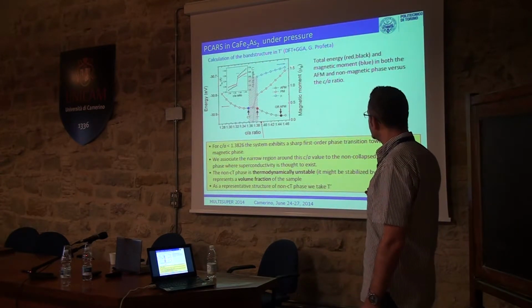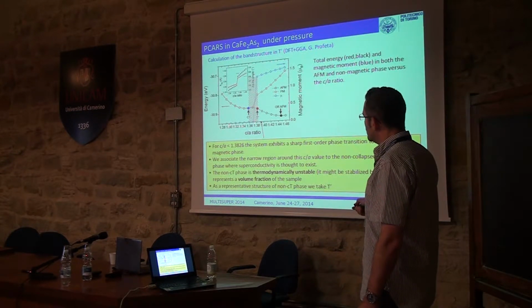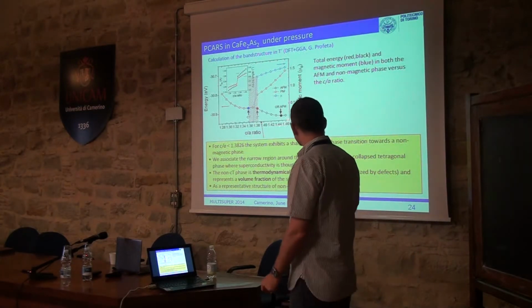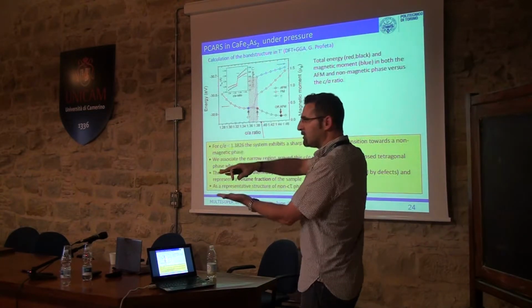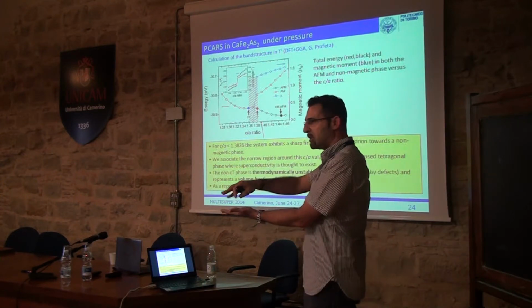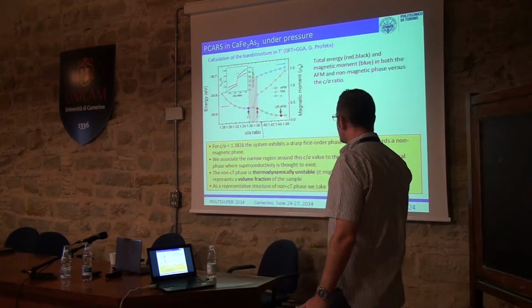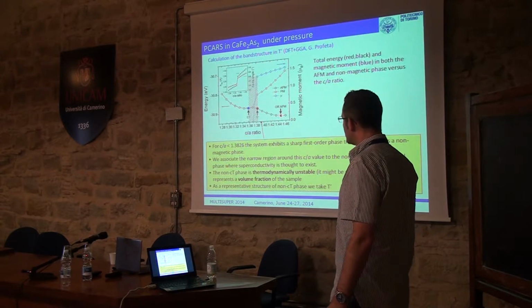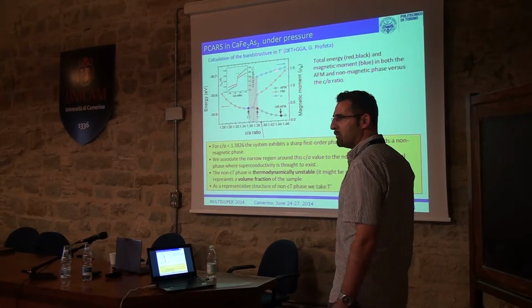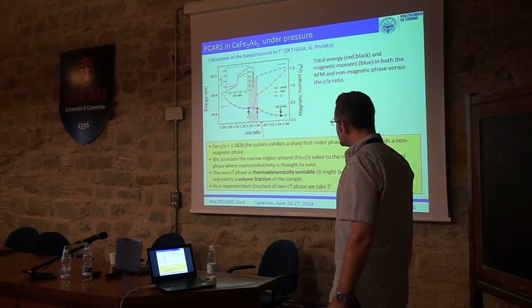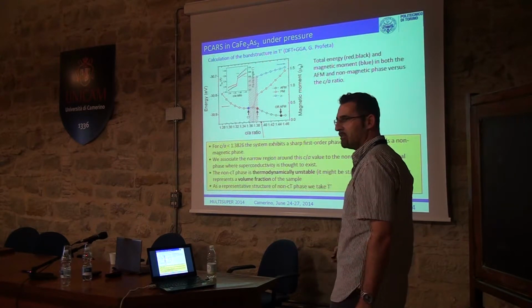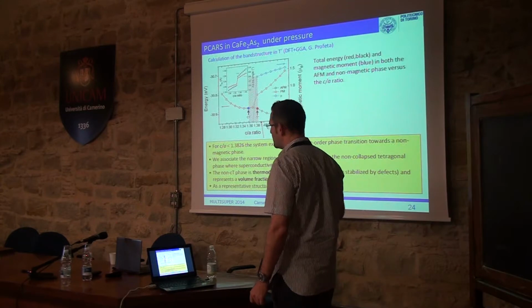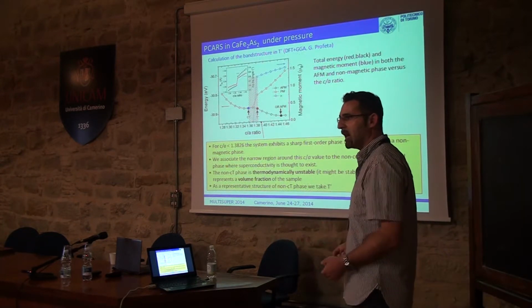You see the total energy in red and black, and the magnetic moment in blue as a function of the C over A ratio. That means moving from here to here, I'm compressing the C-axis. This is what the uniaxial pressure does. There is a first minimum in the total energy. This corresponds to the orthorhombic antiferromagnetic phase, and the magnetic moment is of the order of 1.5 μB. When the pressure is increased, you find a second minimum, which is the collapsed tetragonal phase, and you can check that the value of the parameter is perfectly in agreement with what was found in hydrostatic pressure.